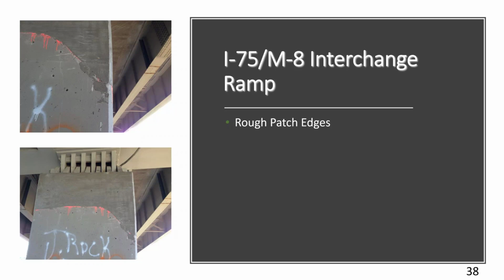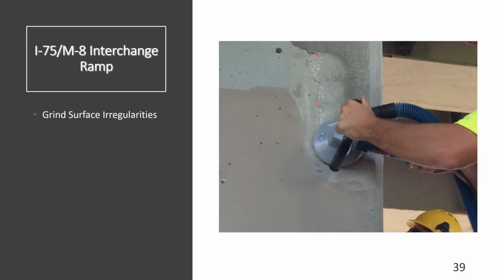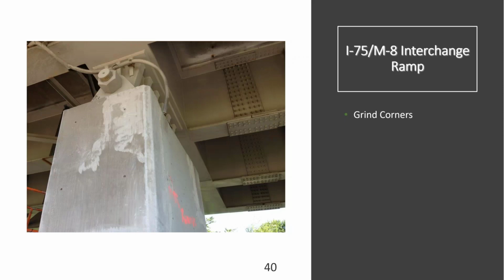Here we are preparing the column surface with a grinding wheel. And also, after we ground all the edges of the patches and all the surface irregularities, we then needed to go in and grind the corners. The fabric we were using required only a 3/4 of an inch minimum radius.